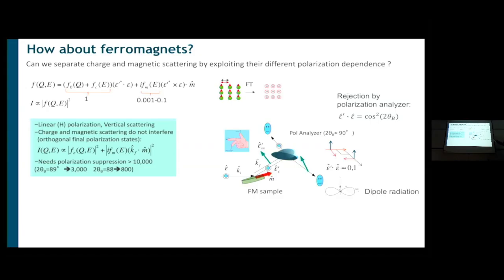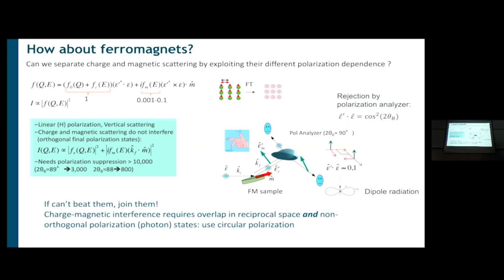But you need a 90-degree reflection to actually suppress this charge scattering, and it's almost impossible to find a crystal that will have a Bragg peak at 90 degrees at that resonant energy. So usually you get to 87, 85, 82, and the suppression factors, when you look at this term, are not large enough. You can maybe suppress a factor of a few hundred, but not a factor of 10,000 or more than you need. So that's a little bit of a problem.